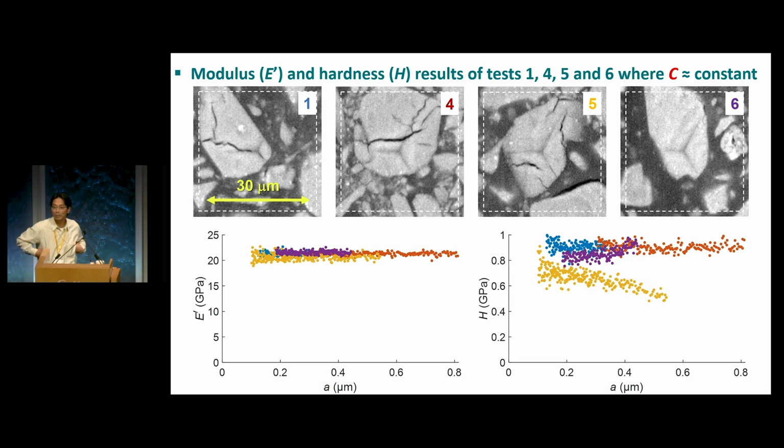Yeah, so if you have that situation where the particle has a very small depth, then you would feel more of the effect of this compliance resulting from this interface to the more compliant material. So I think this is probably the example. And of course, we monitor the compliance, and if the compliance behaves strangely, which happens in other cases, then that's when we exclude the results rather than trying to interpret them.